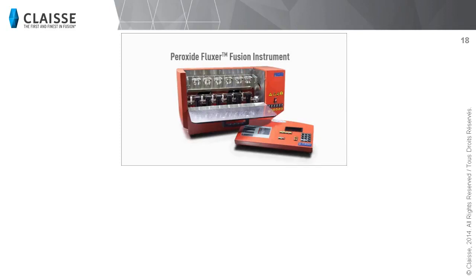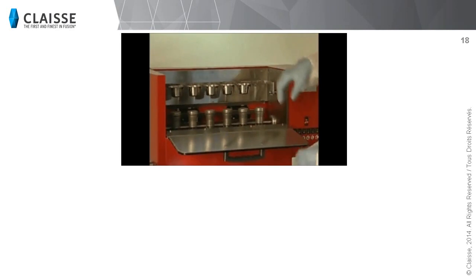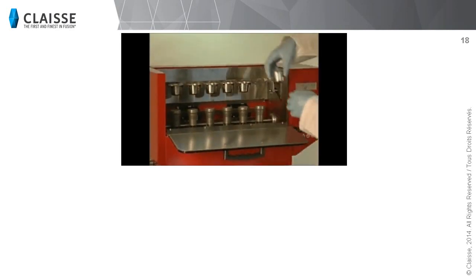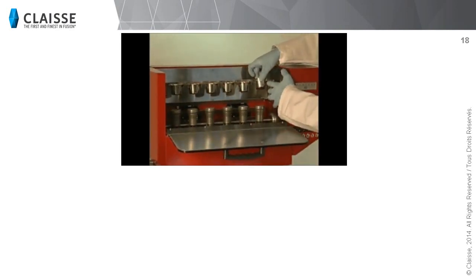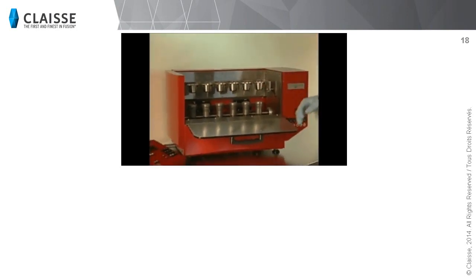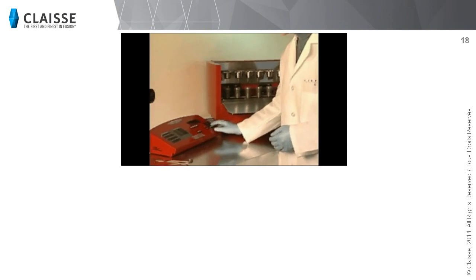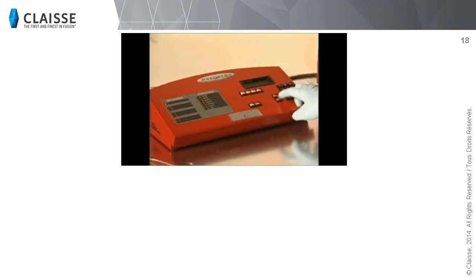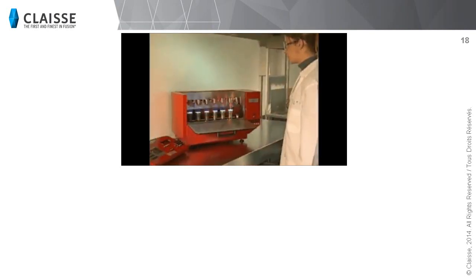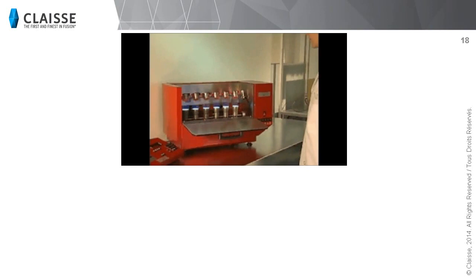First of all, in a zirconium or nickel crucible, you weigh the sodium peroxide or carbonates that will be used to oxidize your sample. Then you add your sample in the crucible. Place the crucible on your sample preparation equipment, as you can see on the video that shows a peroxide fusion instrument. You heat up the mixture at a temperature of approximately 500 degrees Celsius to let the sample react with the peroxide. You let the mixture cool down when the reaction is completed.